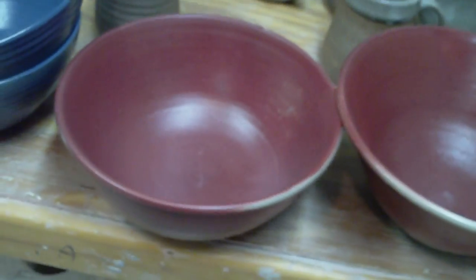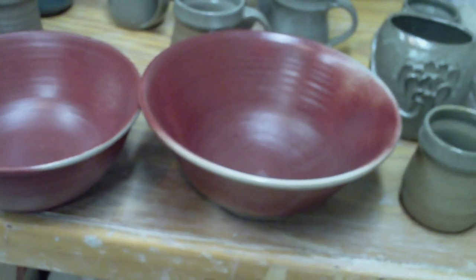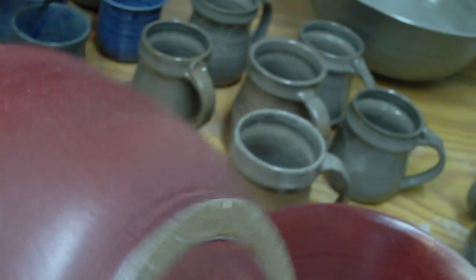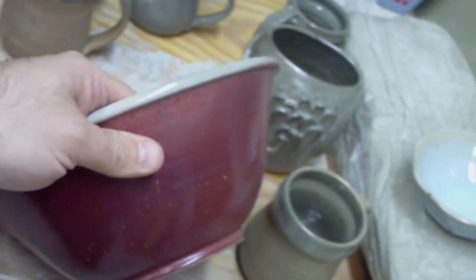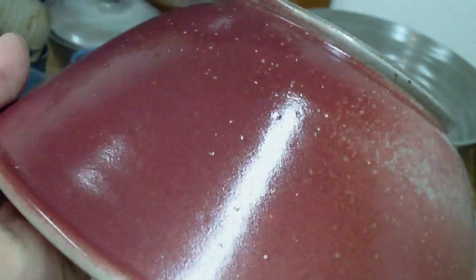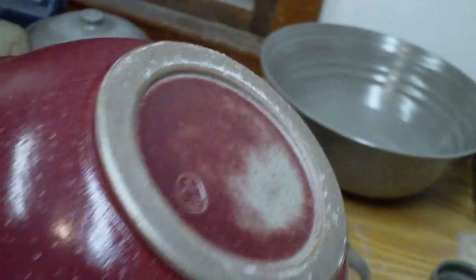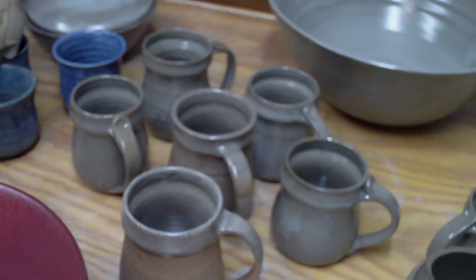These are Jeff's red — I'm happy I got the red color, but I'm not happy because it's not fired to maturity. It's very matte, very rough, I wouldn't trust these for food. That bowl is a good shape but it's loaded with pinholes — it fired but didn't fire to maturity, didn't give the glaze a chance to smooth over. Just not a good firing in general — it happens, and for me it happens more often than not.